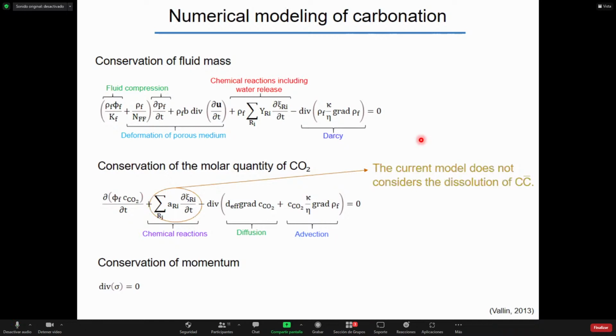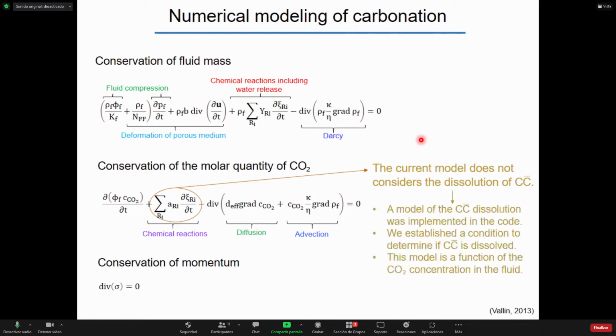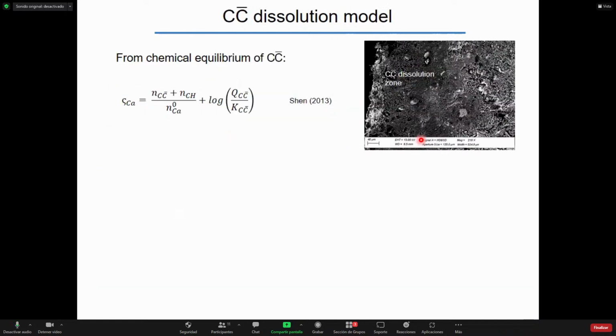However, the current model does not consider the dissolution of calcite, as we have seen in the experimental tests. So a model of the calcite dissolution was implemented in the code by establishing a condition to determine if calcite was dissolved at a particular point. And this model is a function of the CO2 concentration in the fluid.